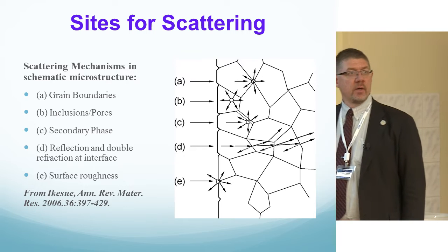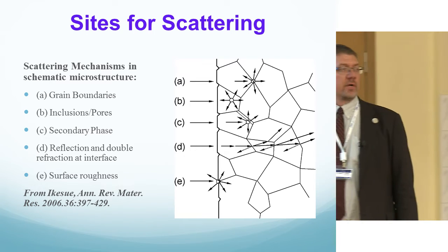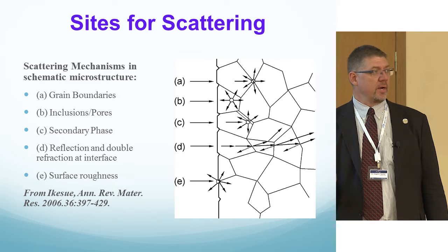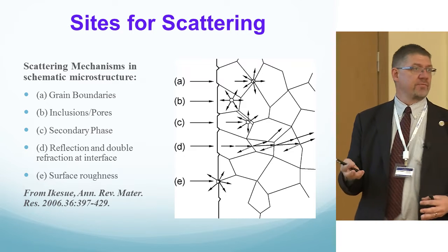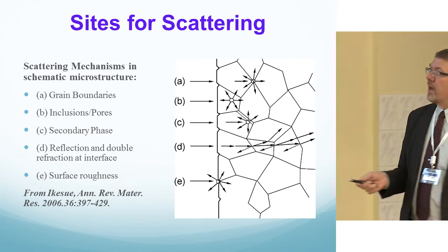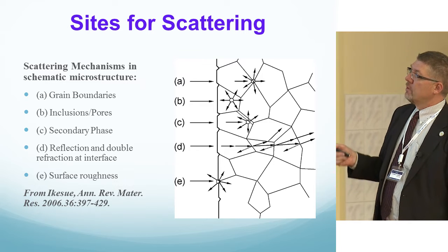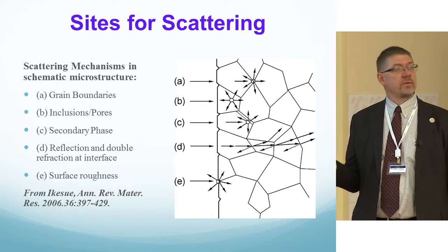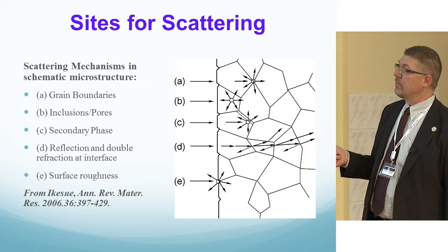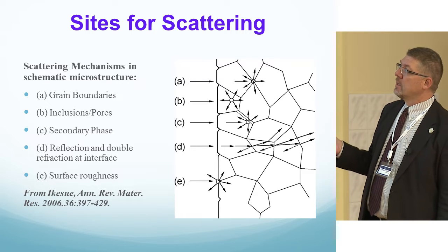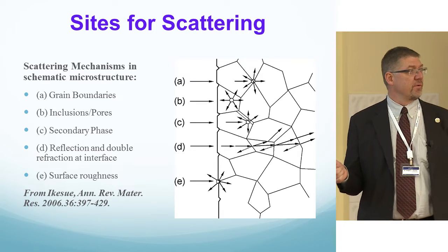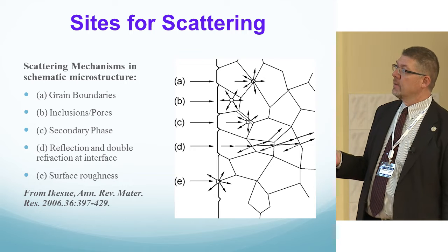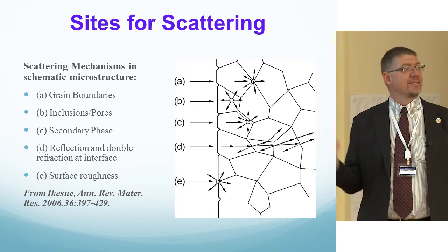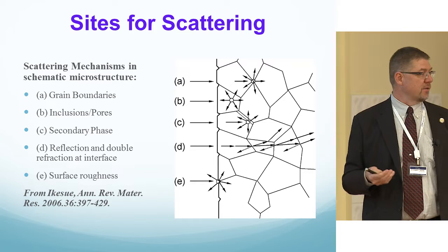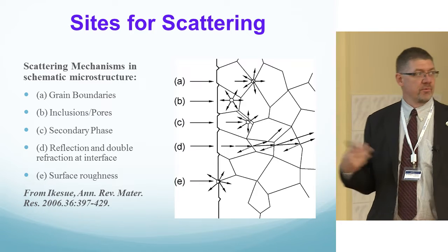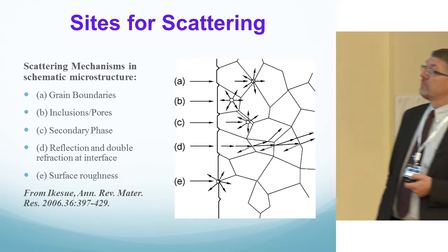Secondary phase. YAG actually has three phases. You've got your garnet phase, a perovskite phase, and an M phase. If you get a mixture of phases in there, the light's going to scatter at each of those different phases. You've got Fresnel losses at the surface. That's going to happen with any difference in the index of refraction, but you can also have double refraction at interfaces if they're not aligned properly. And then finally, surface preparation. That can be solved through fabrication and polishing. All of the others come in through the manufacturing process.